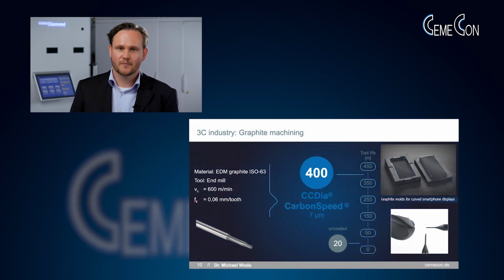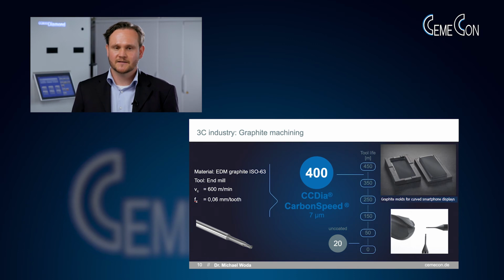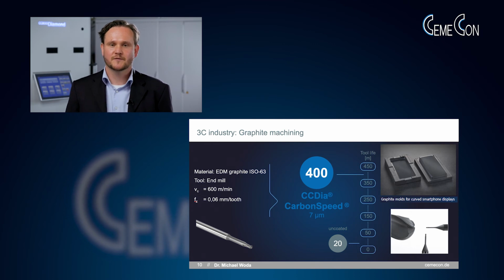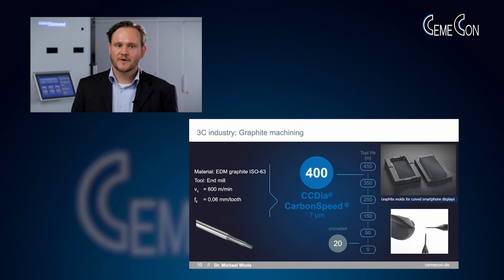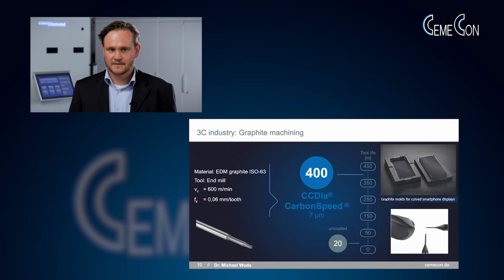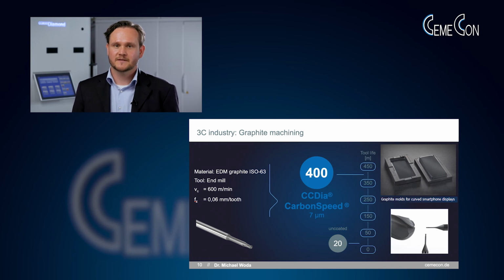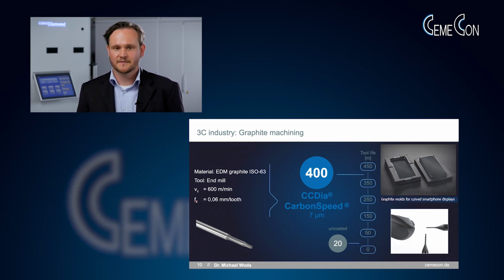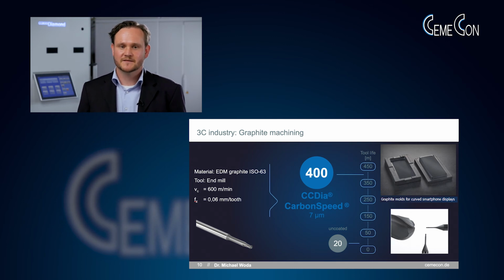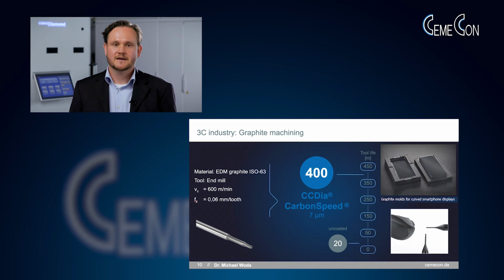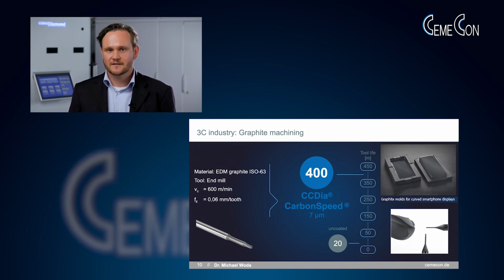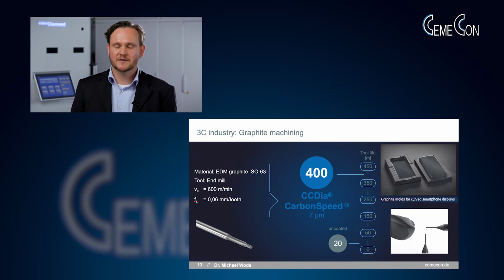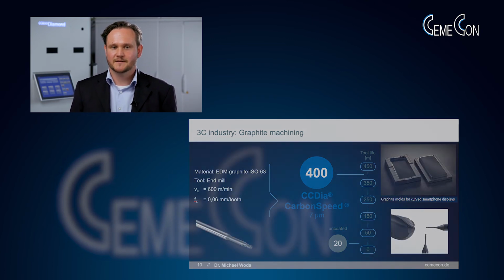Graphite milling has always been an important topic for diamond-coated cutting tools. In the upper right picture, we see a typical example of a mold used for modern mobile phones. In a comparative case study, here we examine the machining of graphite milling with diamond-coated cutting tools. Again, we start with an uncoated reference and detect a value of 20 meters cutting path. In contrast, we have 400 meters boost in tool life when we use the diamond-coated tools. This factor of 20 is a typical number when applying diamond coatings onto tools and machining graphite.